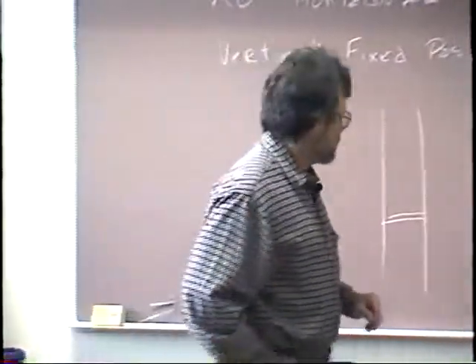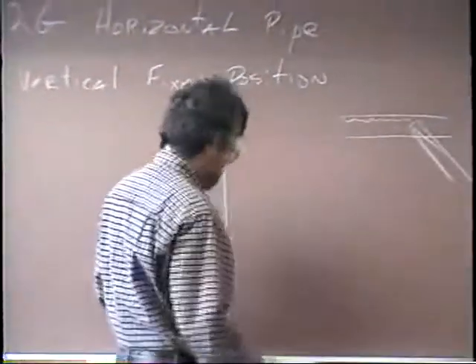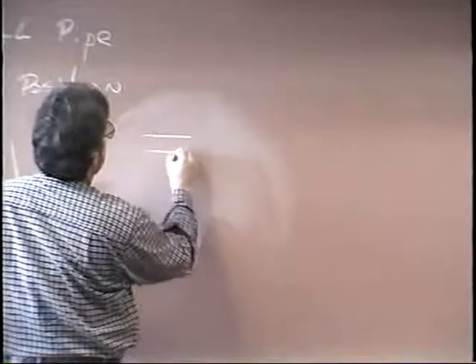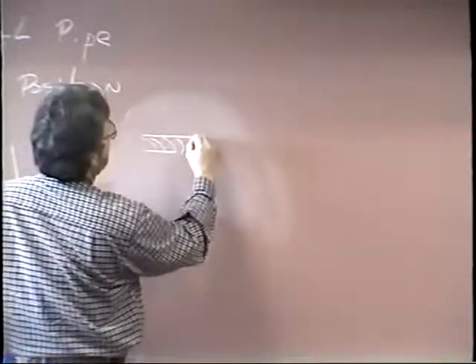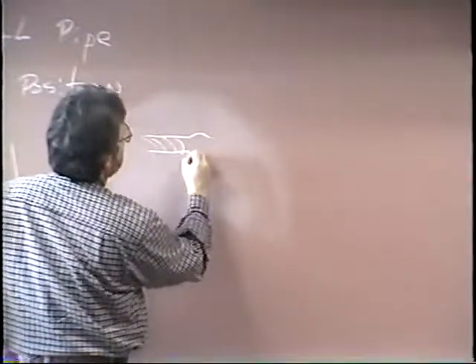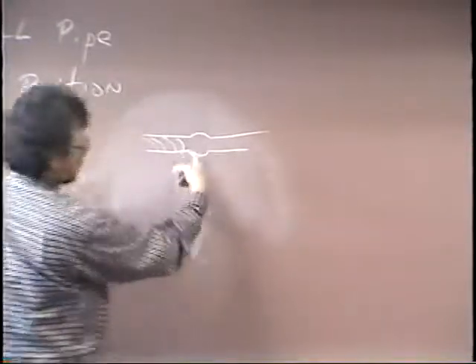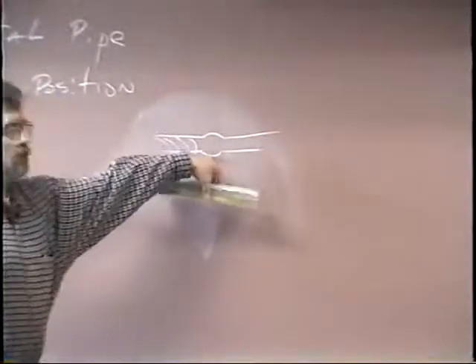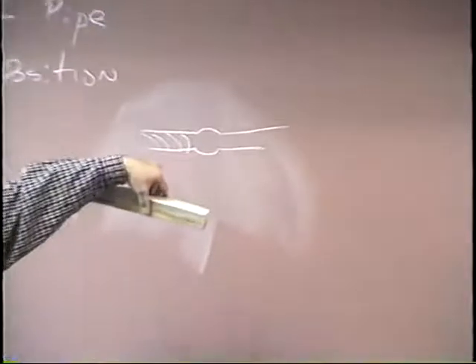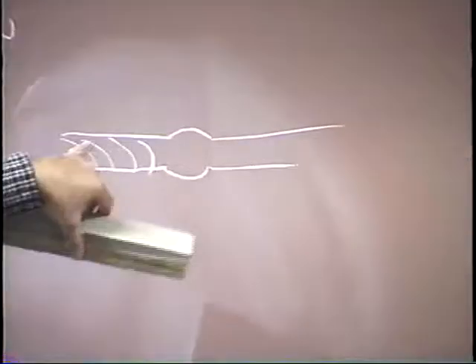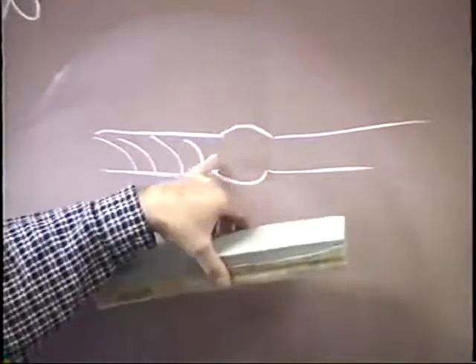You want to establish your keyhole, just like in pipe welding or plate welding. You want to make sure that you've got a keyhole here, so that here's your bead, and that keyhole is eating into the bevel, like so. If you don't see that keyhole and you don't hear that sound of ham and eggs or bacon and eggs frying in the frying pan, you're not getting penetration. So you want to watch that keyhole as you're coming across on there.